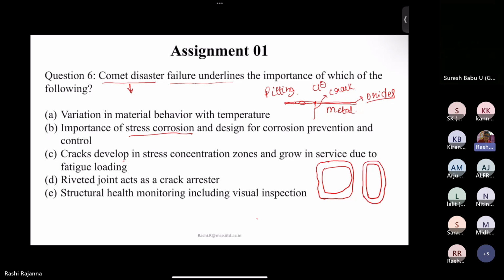So at this region, even if a small crack gets formed, it not only acts as a crack, but even though the size of the crack is very small, it acts like a hollow, that's why it acts as a very big crack, and it gets easily propagated and grows severely due to fatigue loading, as the cabin will be pressurized and unpressurized. Because of this, it gets easily propagated, and because of the fatigue loading, it failed mainly. So C is the right answer.